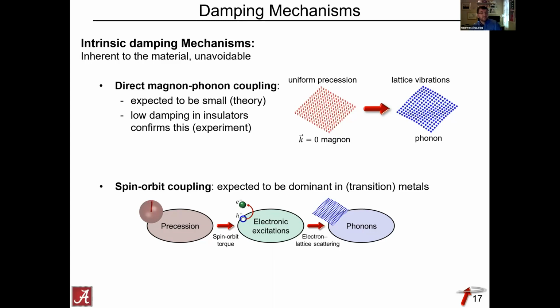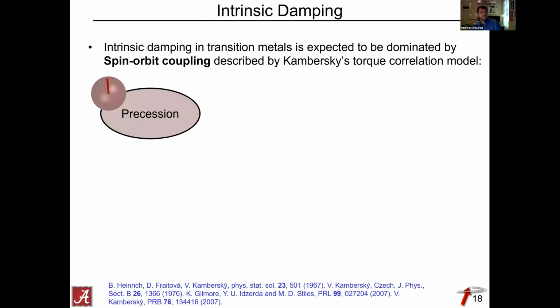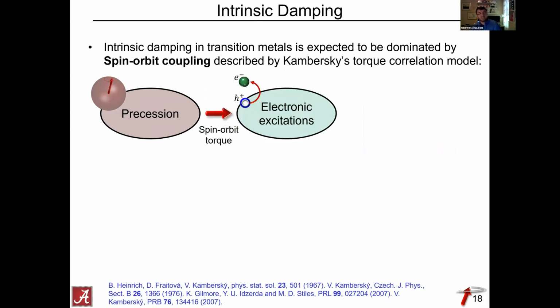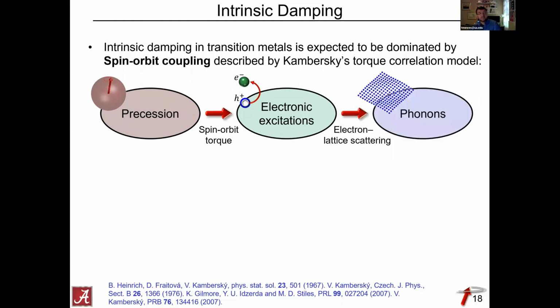Instead, in transition metals, spin-orbit coupling is actually the intrinsic damping mechanism that we need to consider. Let me show that in a little bit more detail. Kambersky, way back then, together with Brett Heinrich, came up with this model. Essentially, the precession of the magnetization is able, via spin-orbit torque, to create electronic excitations, which in turn, via electron-lattice scattering, create phonons. And so that's your dissipation channel.